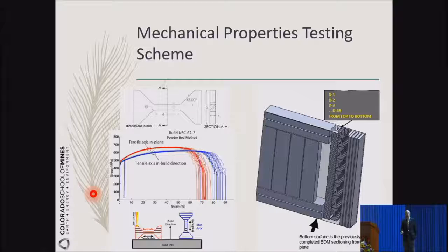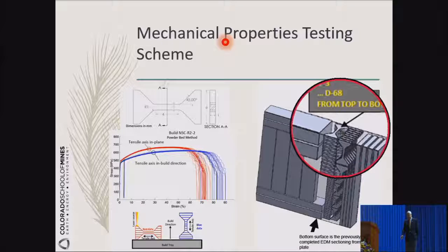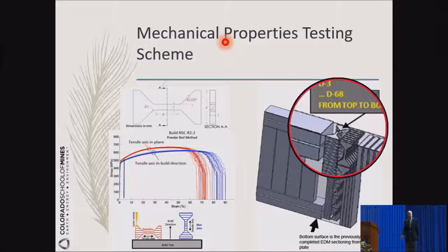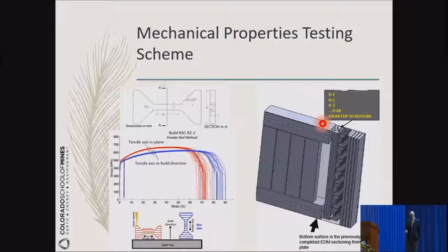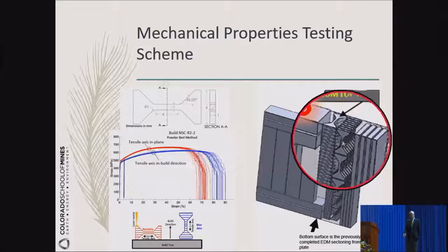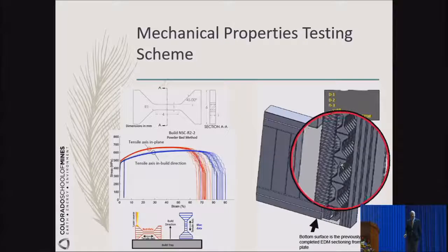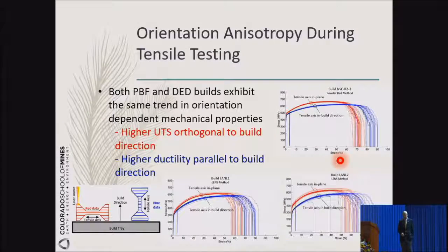Another one that people look at a lot about anisotropy is the mechanical properties. So here, this is a look at the tensile specimens. Some are parallel to the build direction, where the arrow is. And on the other side, these are transverse. I'm going to go to the next slide here. You see that they are different. They exhibit different properties. The blue lines here are in the build direction, and the red lines are transverse, orthogonal to the build direction. Invariably, the red lines have higher strength but lesser ductility, and the blue lines lower strength but higher ductility.